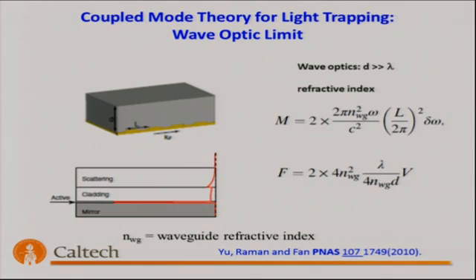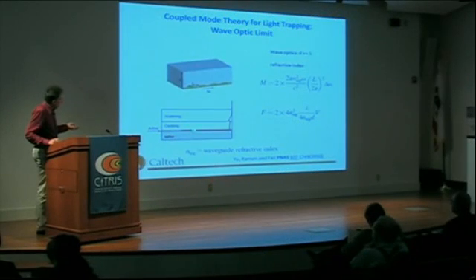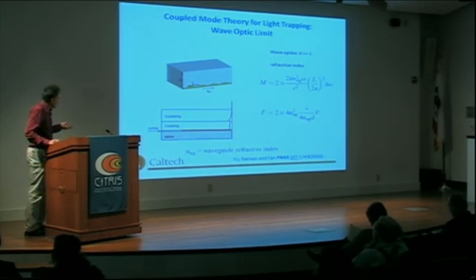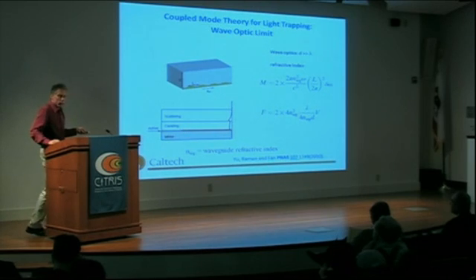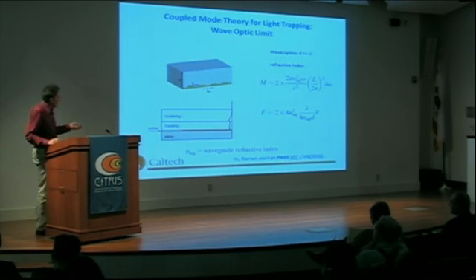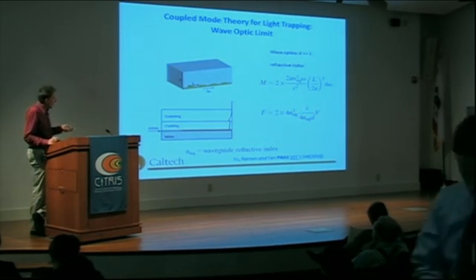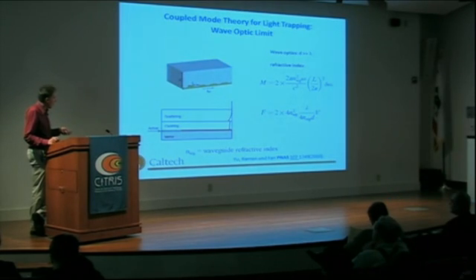So for example, if we have a wave in a low index material that would have a low light trapping intensity factor due to its low index in the bulk, if that mode is highly confined near a high index material, like a metallic mirror, and say trapped in between that high index metallic mirror and a high index cladding layer, then the effective mode index, the waveguide mode index, can be considerably higher. And then this light trapping factor now has a factor here of 4n squared lambda over the waveguide index. And so this guide index can become very large, and this factor can now, in principle, exceed 4n squared.